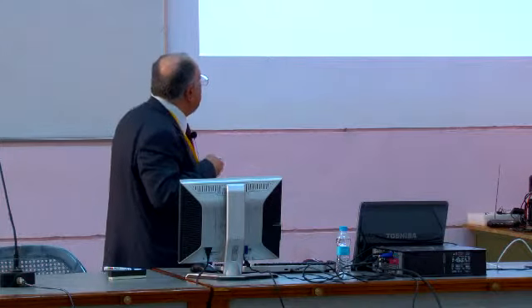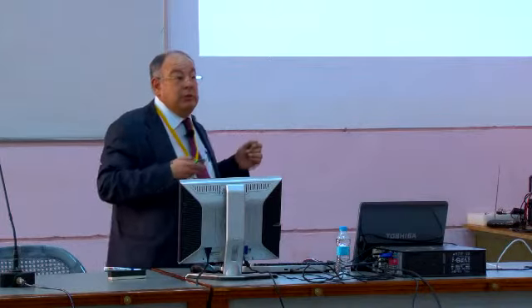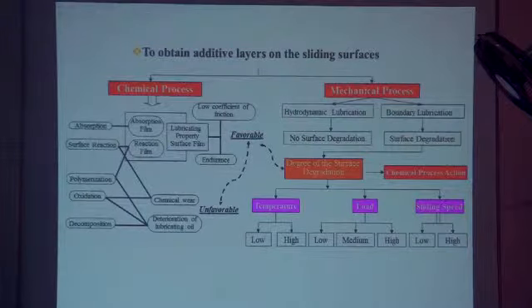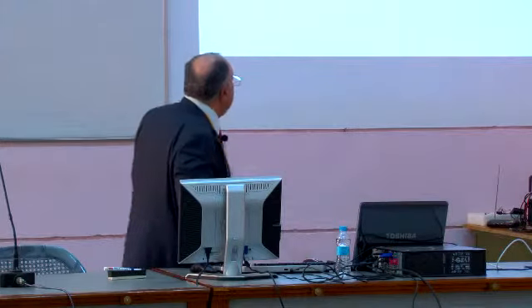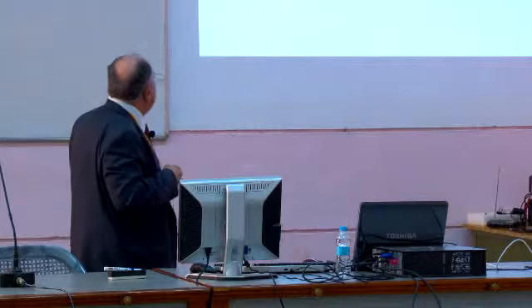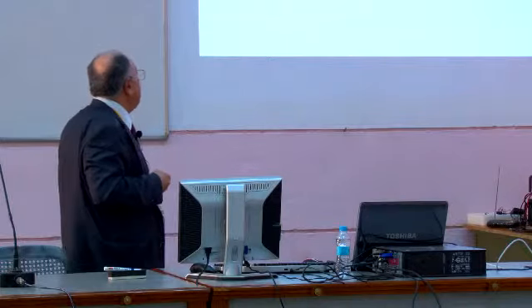The surface must be degraded, but the degree of degradation matters. If it's dry friction, the surface is much more degraded and the additives do not form properly on the surface. This degradation is very important—it must be slightly degraded to make the surface attractive, with a bit of flatness, suitable conditions that favor chemical reactions. So all the chemical reactions occur and you get a layer on the surface. Of course, temperature, load, and sliding speed, which are mechanical conditions, affect the formation of these layers.